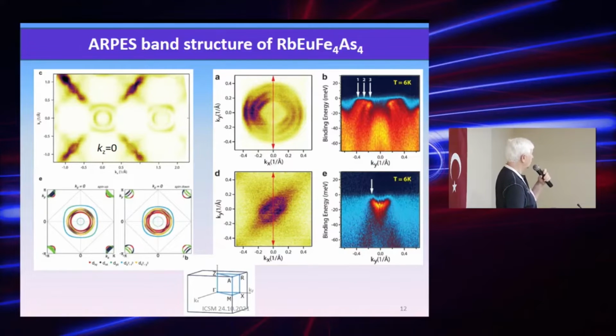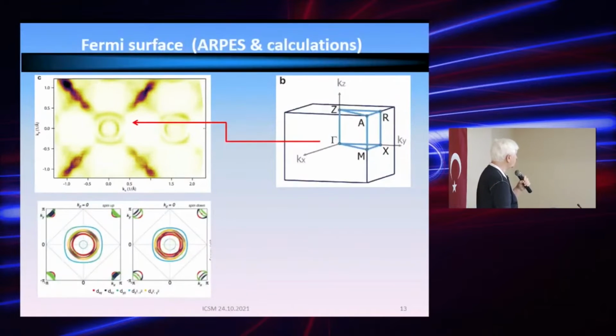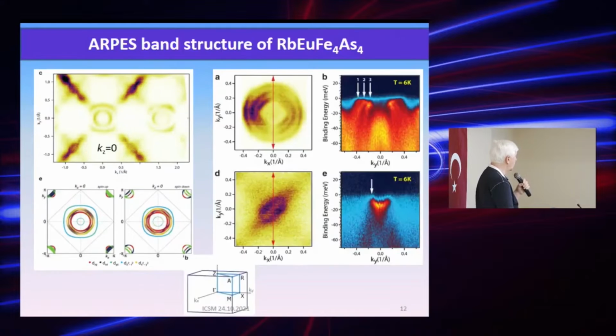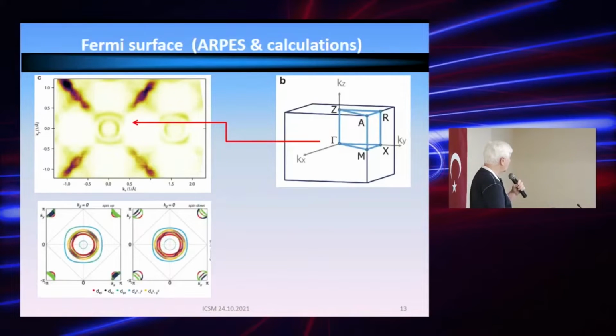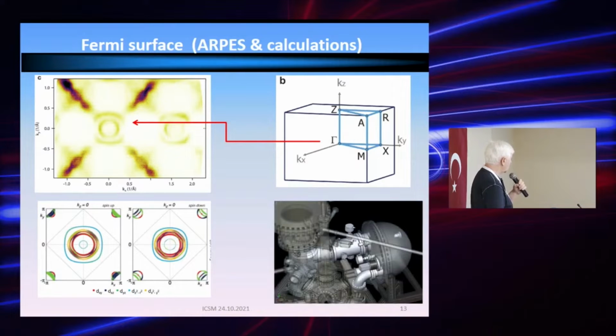So experiment reveals nicely the valence band belonging to these cylinders and the electron bands, which are located at the endpoints of the Brillouin zone, and extend up. Again, this picture shows where these results can be identified with gamma points, and previous results can be identified with the endpoint of the Brillouin zone. So everything is clear here and understood, and I don't see any puzzles. So far, so good. And this is done in the ARPES machine.